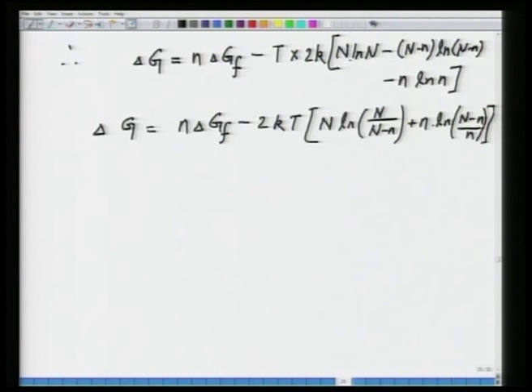So if you just do this, N ln N minus (N minus n) ln (N minus n), you can take the N out, make it N ln of N divided by (N minus n), and this would become plus n ln (N minus n) minus n ln n. So you take out small n, and then this would become n ln of (N minus n) divided by n. So this is very simple to do.